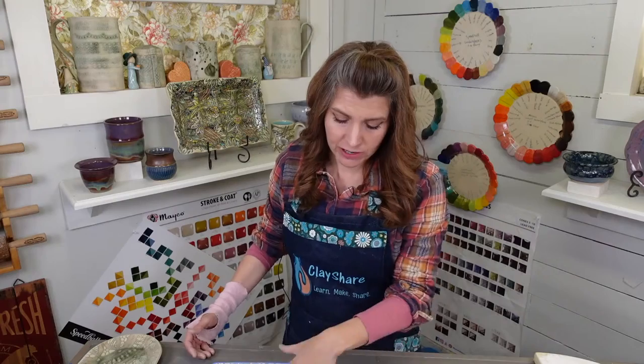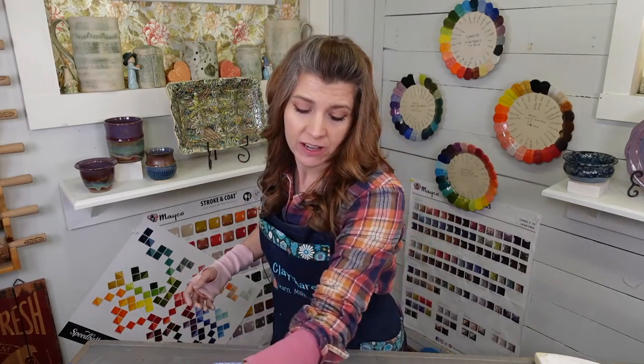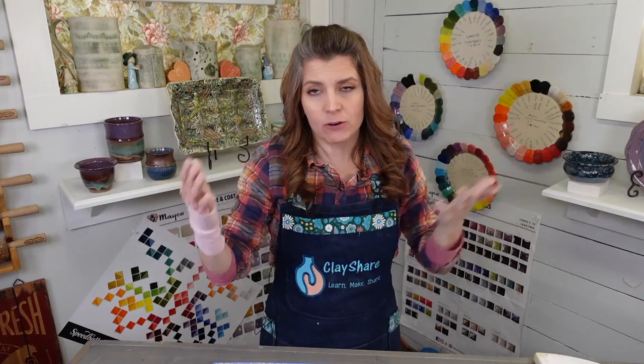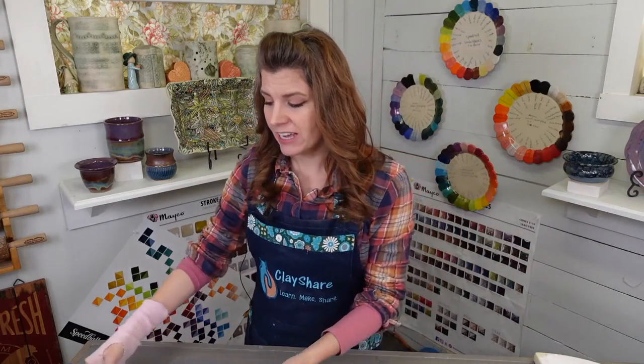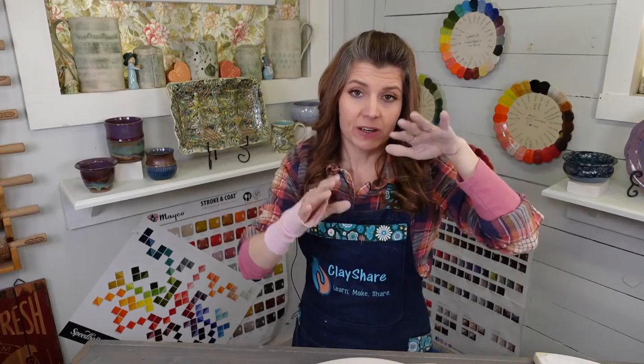After you have a nice form with no wobble and everything's great, you're going to fire it in the kiln. Make sure the kiln shelves you're using are nice and flat. Over time with use, kiln shelves start to bow a bit. Because I put kiln wash on one side, my kiln shelves only face one direction — I don't flip them, which could counteract the bowing, but I don't want old kiln wash falling onto my pieces. Make sure you have a nice flat kiln shelf for both bisque and glaze. Never span your platters across two shelves. That gap can cause heating and cooling unevenness which causes warping, and it could also be one side a little higher — setting yourself up for cracking.